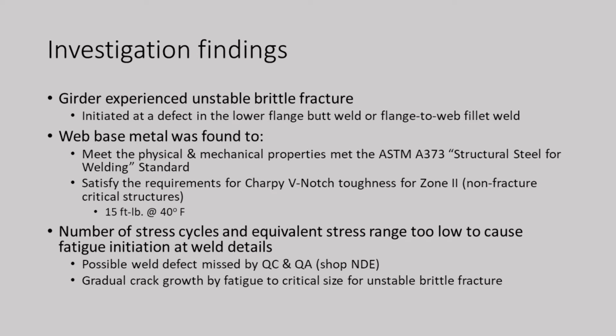And we found for the details that were present, basically they were just attachment welds to the major pieces. The stress ranges were too low to cause fatigue initiation due to weld details. So we're only left with the possibility that what we saw as that artifact in the middle, we thought was a weld defect, is a weld defect. Probably came out of the fab shop.